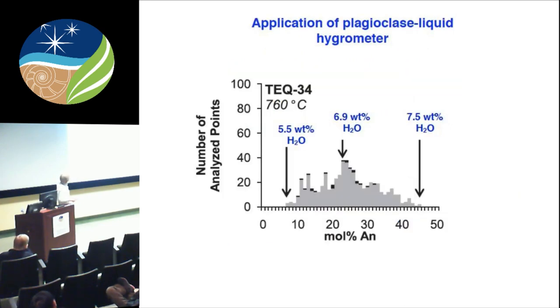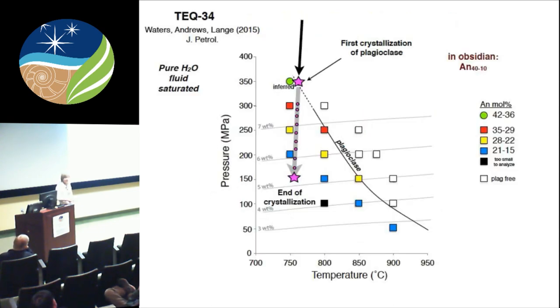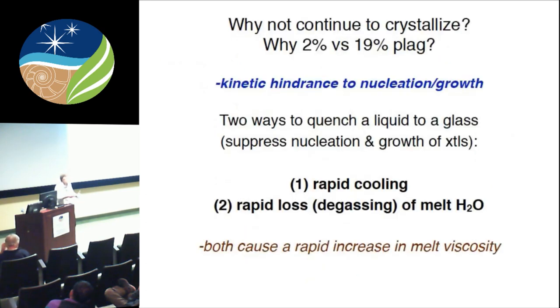Okay, but what's causing such a low abundance of plag? Remember, by the end of crystallization, we should have 19% plag, and it still hasn't gotten down to anorthite 10. And it also just seems to stop. I mean, crystallization doesn't continue. So what could cause that? So why not continue to crystallize? Why 2% versus 19? So what we're hypothesizing is that it's because of a kinetic hindrance to nucleation and growth that's causing this low abundance.